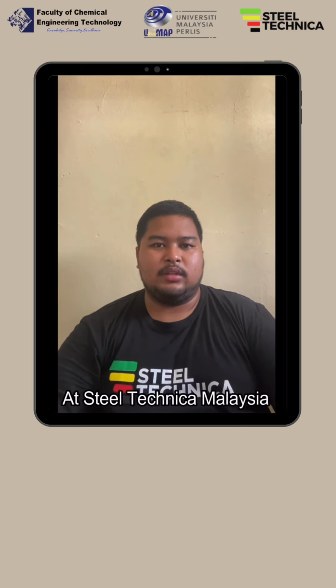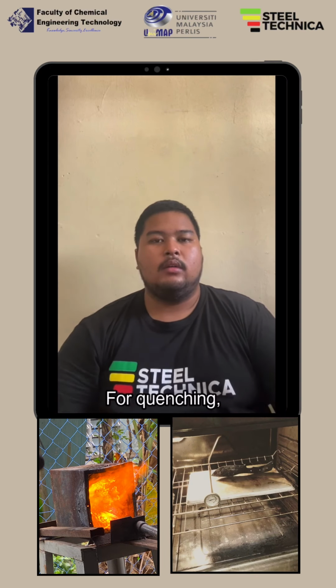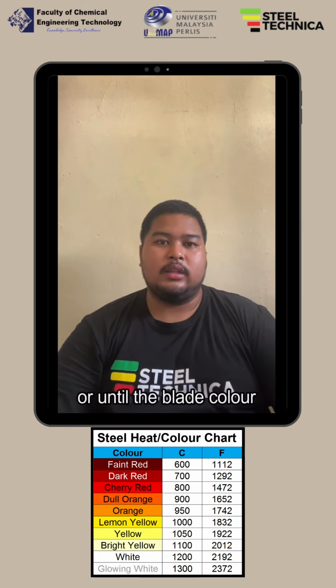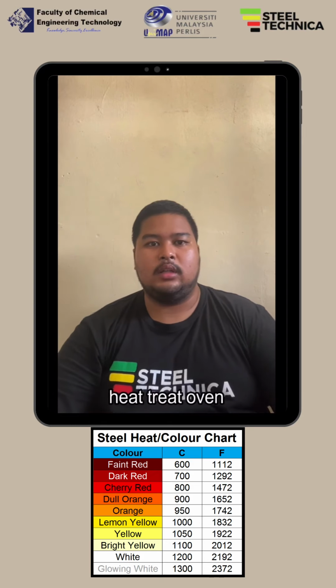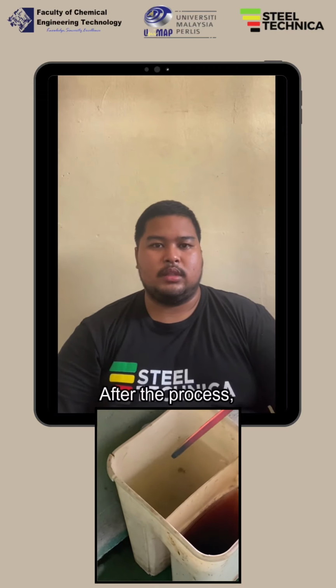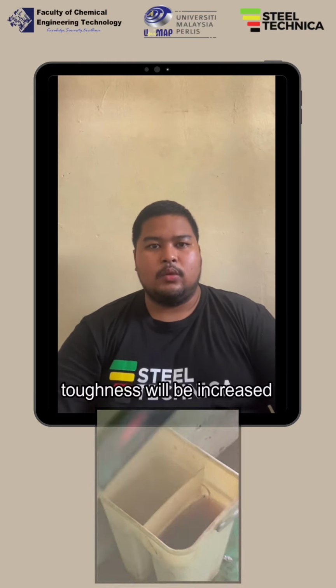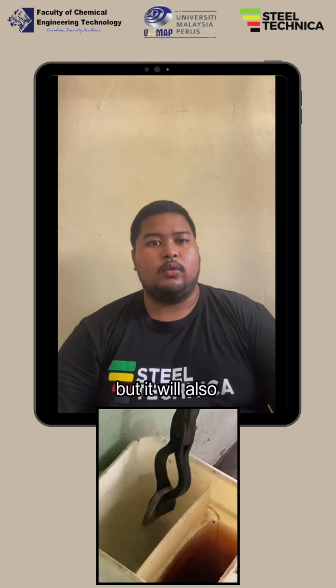Next is heat treatment. At Steel Technica Malaysia, we do two types of heat treatment, quenching and tempering. For quenching, we heat the blade to 900 degrees Celsius or 950 degrees Celsius, or until the blade color turns orange, in a heat treat oven. Then quickly cool it using oil or water. After the process, the knife hardness will be increased, but it will also become brittle. As for the cooling medium, we usually use oil because it reduces the risk of distortion or cracking by cooling the metal more evenly and more quickly.